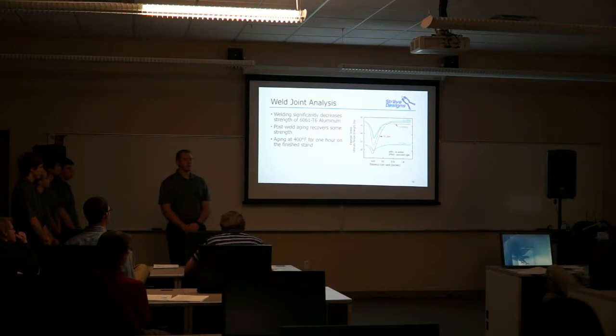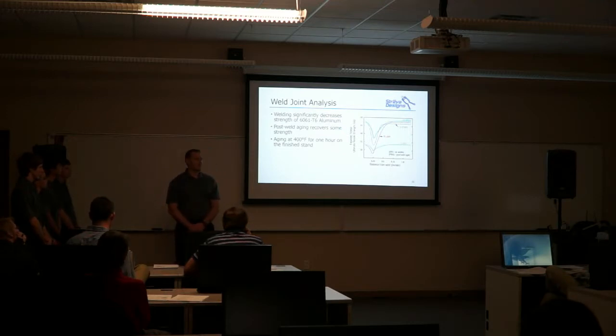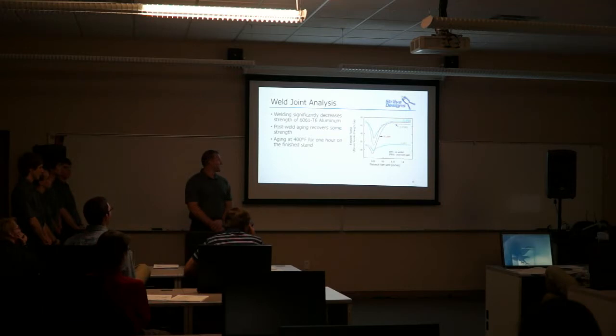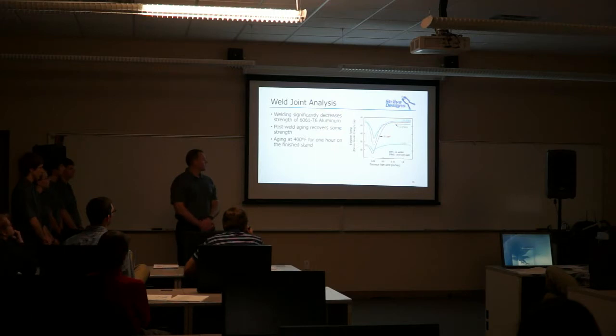As discussed earlier, welding significantly reduces the ultimate tensile strength of the material. Shown in the diagram on the right is how much the tensile strength is reduced in regards to distance from the weld. As you can see, the strength at the weld remains fairly stable. However, approximately a quarter inch from the weld, there is a significant reduction, and with a T6 heat treatment, the reduction is approximately 50%. Some of that strength can be recovered